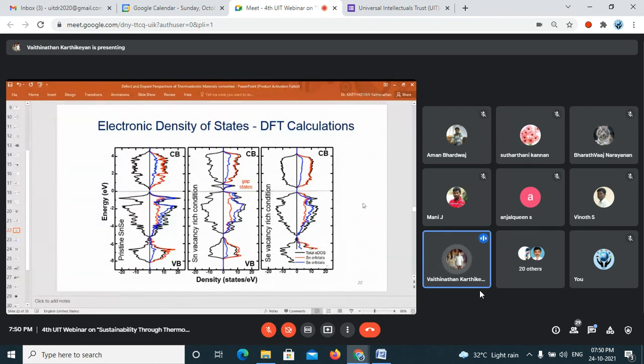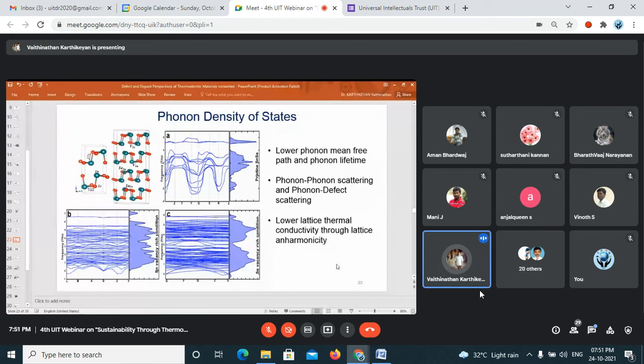This is also the electronic density of states calculation. Here, this is for the pristine one, and with the defect one, you see the formation of a gap state here, which is responsible for the trapping and reduction in the electrical conductivity. This is observed in the case of tin vacancy, not observed in the case of selenium vacancy. And then this is the phonon density of states, and this is the electron density of states. When the number of states increases, scattering increases. For example, if you are walking through a cloud, your speed will be decreased, so your time for reaching the other end also increases. In the same way, when there is a smaller number of states, the speed is high, the phonon travels from one point to another very fast, and there are not many bands. Their efficiency is reduced and the thermal conductivity is really reduced.